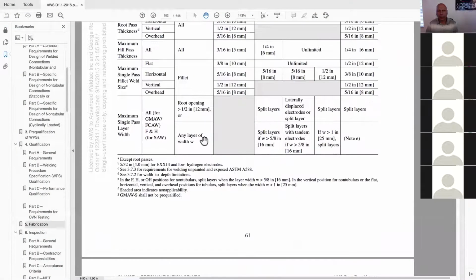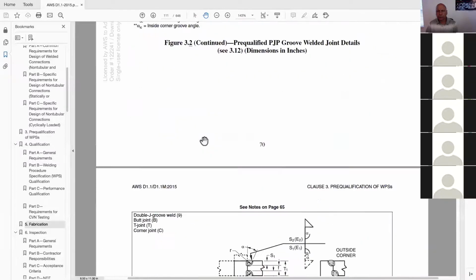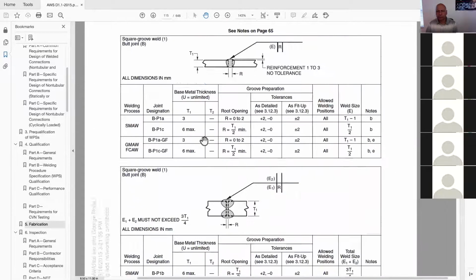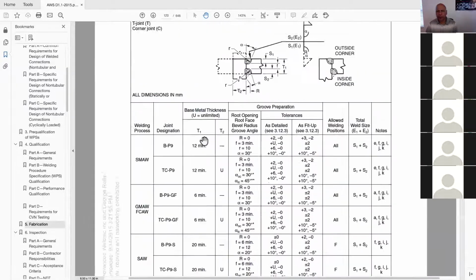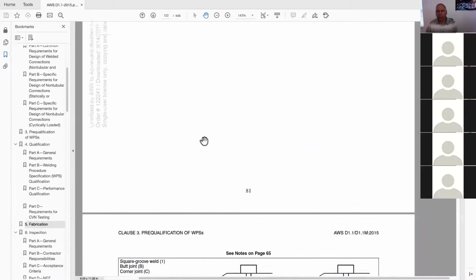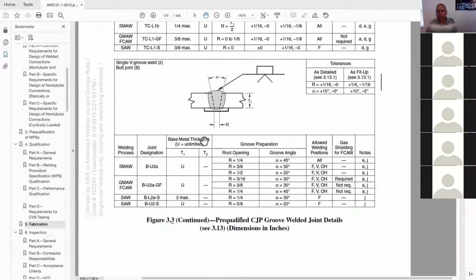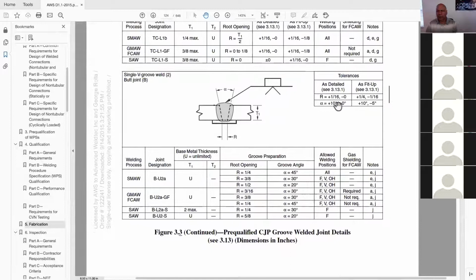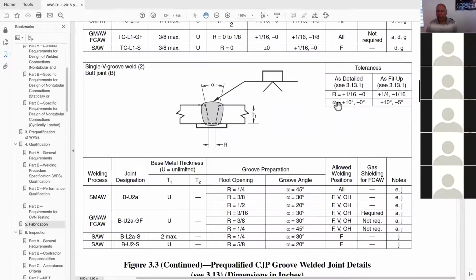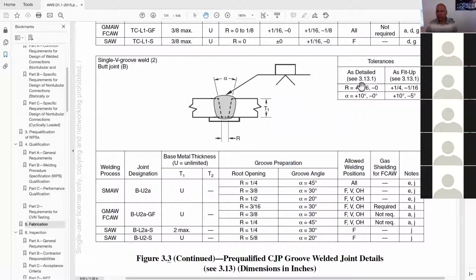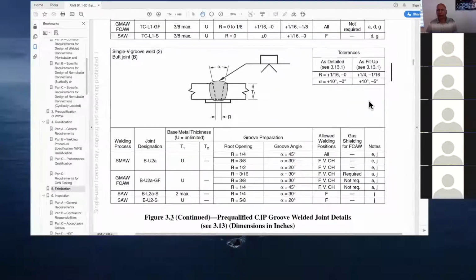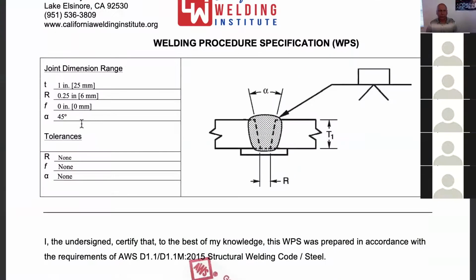If this was a production WPS for this exact same butt joint, single V groove, we would go to the pre-qualified figures of 3.3, and then I would use those tolerances in there, right? I would have the tolerances up here, and in the WPS I would not include a detailed tolerance. I could, for example, go to my WPS for production. Instead of putting a 1/4 inch root opening, I could already in here detail it